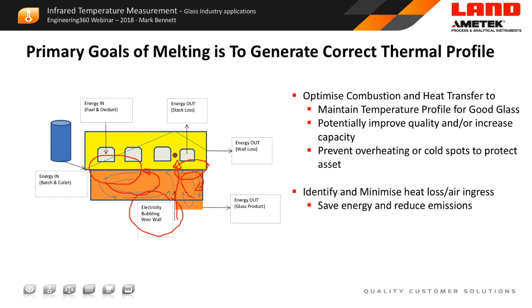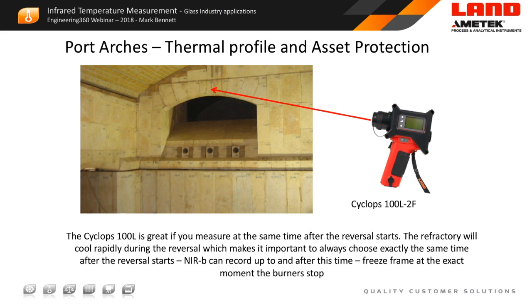Now, to drive these thermosiphons under the surface, the primary goal is to create a temperature profile along the crown of the furnace and along the side walls of the furnace. The key element here is to create what's called the hot spot, which occurs above the spring zone. So as you can well imagine, temperature control, temperature monitoring and flame management are very important within this environment. Traditionally, if you go to most glass plants anywhere in the world, the Cyclops Portable has become the industry standard for monitoring temperatures and temperature stability within a glass tank.